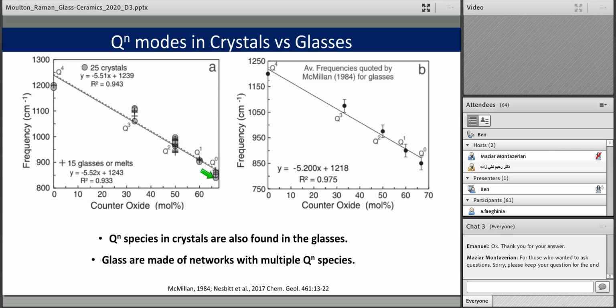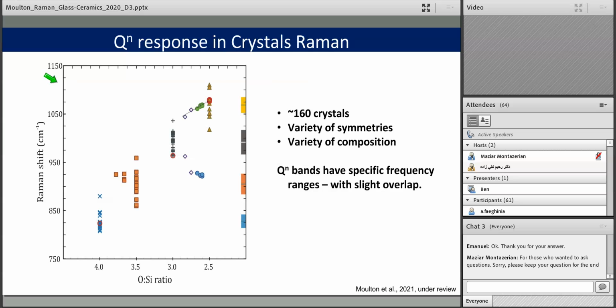So the separation between Q0 and Q1 is about 50 wave numbers, whereas here between Q3 and Q4, it's close to 100 wave numbers, perhaps. So there's quite a strong change in the frequency that is clearly well correlated between glasses and crystals. And this makes that qualitative assertion that there are similar vibrations stand on much stronger evidence.